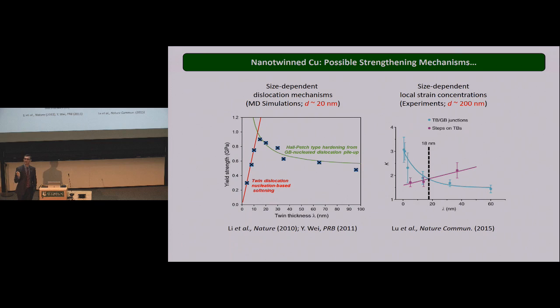Now, there are two problems in this comparison here. The first one is when you look at the grain sizes that are typically used in experiments, they are almost 10 times larger than the grain sizes we use in MD simulation to predict those mechanisms. So there's always a disconnect between the simulation and the experiment. And these mechanisms explain the increase in strength, but they don't clearly explain why the ductility changes so dramatically. And so what truly governs the ductility of nanotwin metals? Again, these materials are assumed to be perfect in the sense that the boundaries inside are perfect.